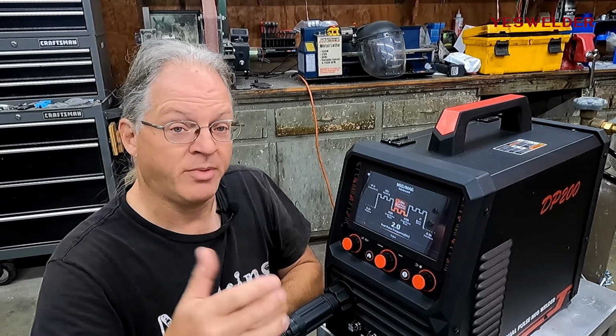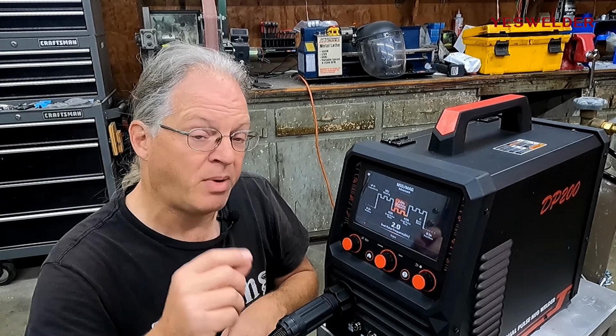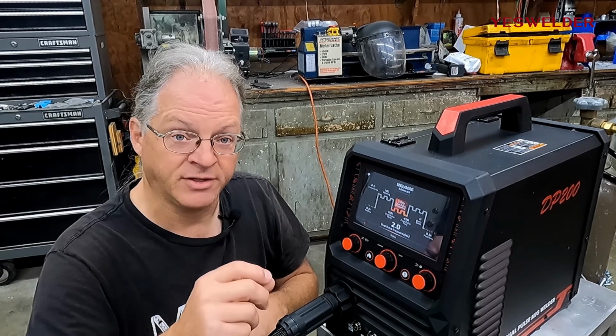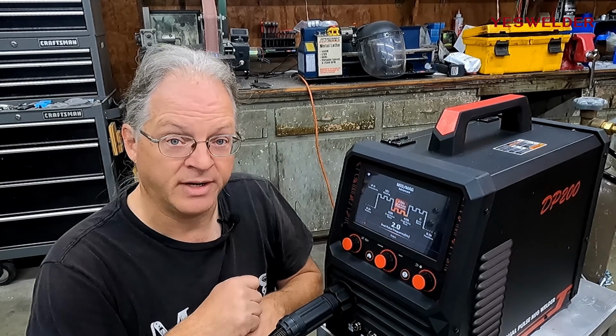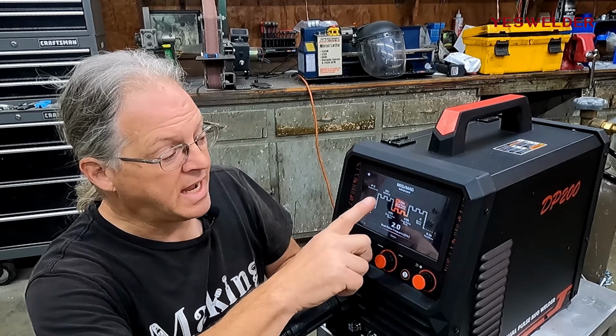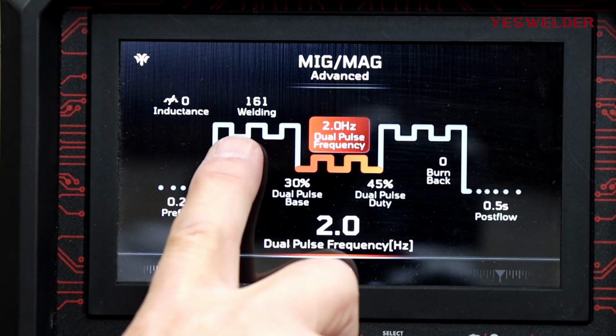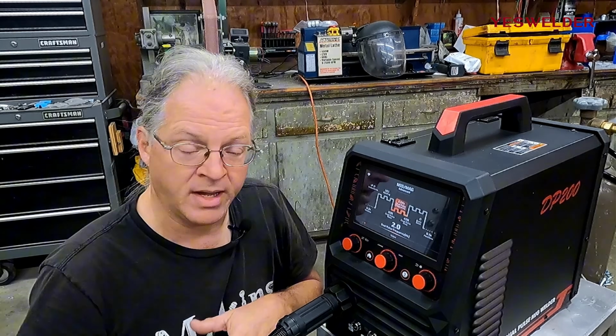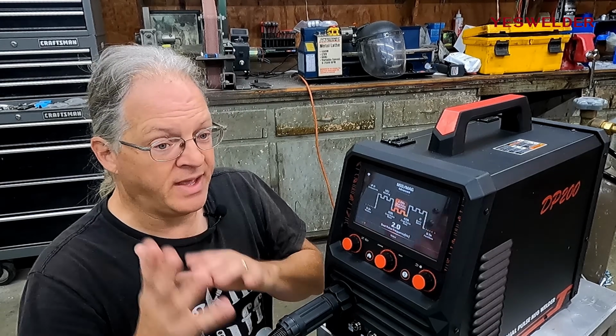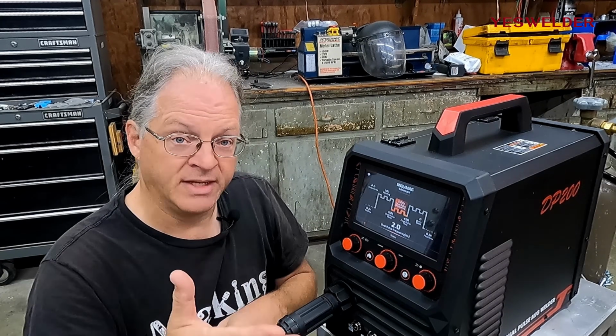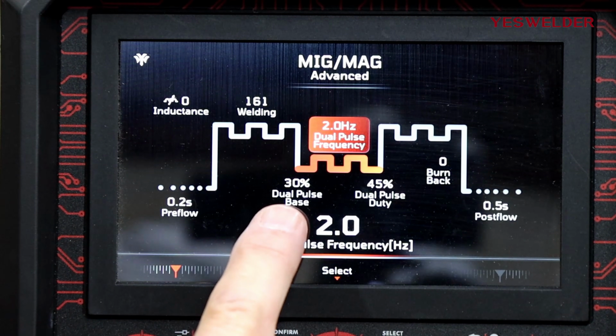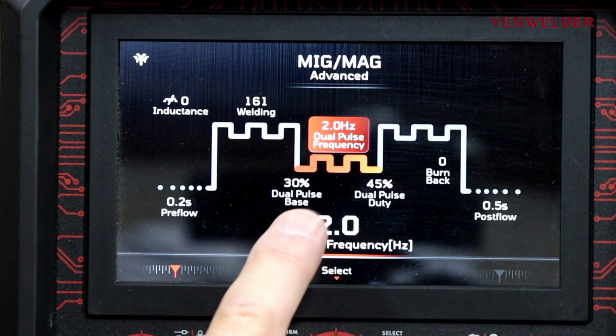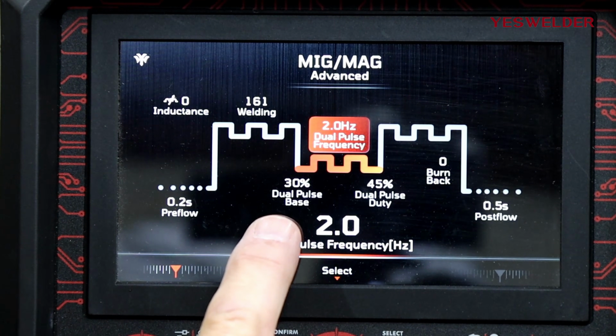Now, if you also remember, I said I was using the default out-of-the-box settings for 16 gauge aluminum that the DP200 is programmed for. That comes out to 161 inches per minute, which is roughly around 80 amps. So another thing I did to keep from burning through and warping this aluminum was I dialed the background or the base current back to 30%.